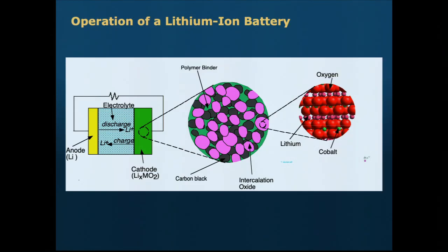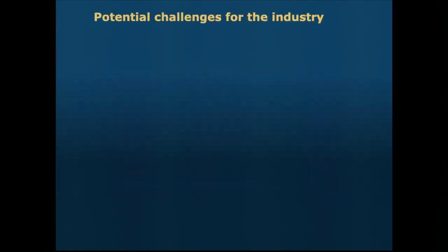The way you store lithium is by intercalation into an oxide. So typically, there are these layered oxides. This is a picture of lithium cobalt oxide, where you have this layered structure of cobalt ions, lithium ions, cobalt ions, lithium ions, and you basically shuttle lithium ions back and forth in and out of the structure. So you store lithium in a material kind of like a sponge, right? In discharge, the lithium sits at the cathode. In charge, you pump it back up electrochemically to the anode, and then in discharge, you release it again.